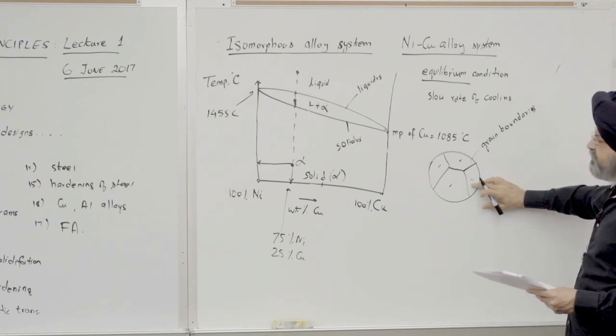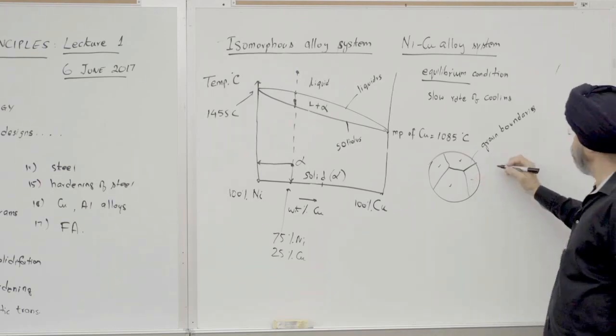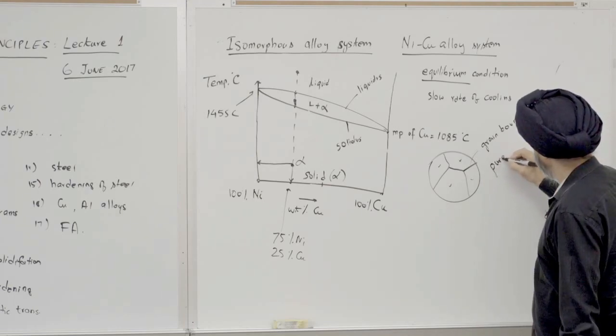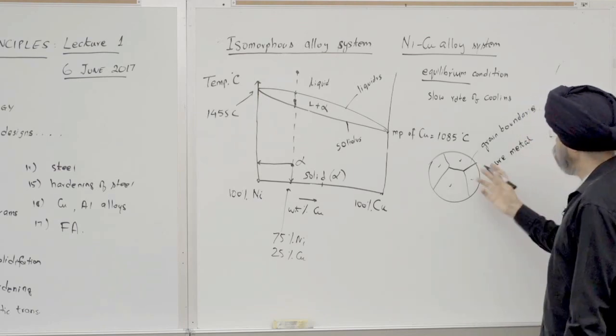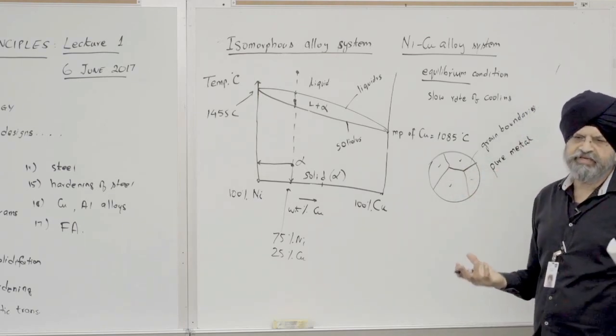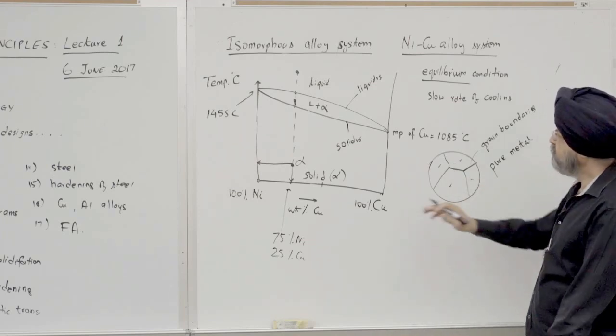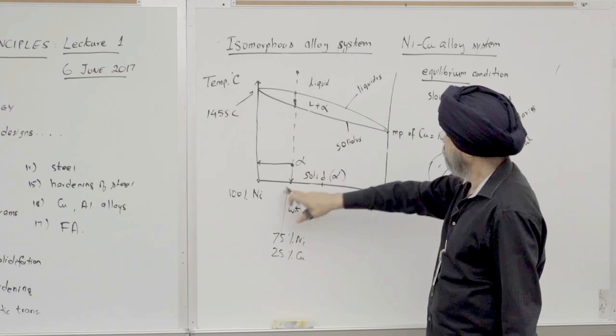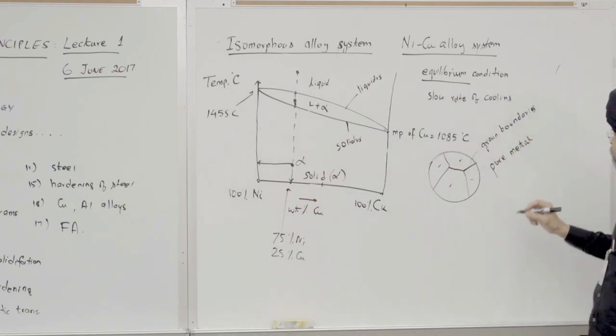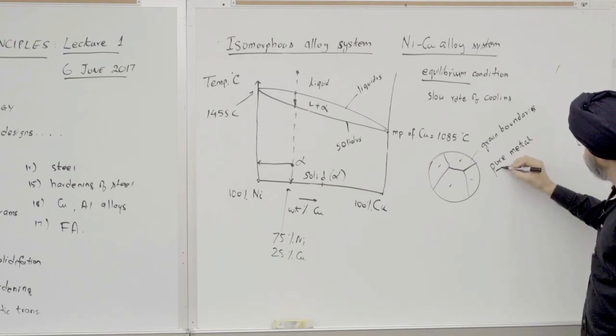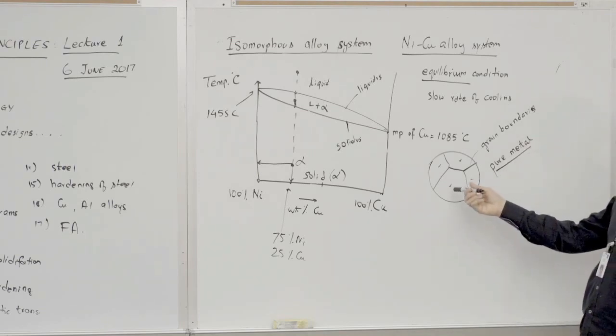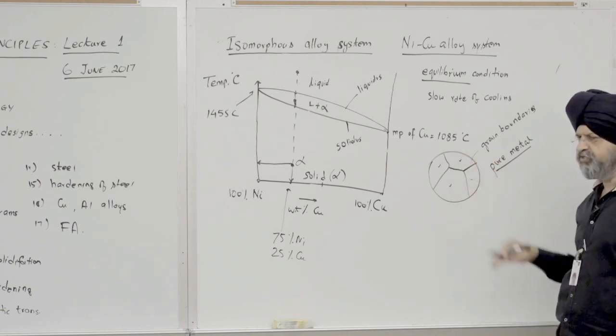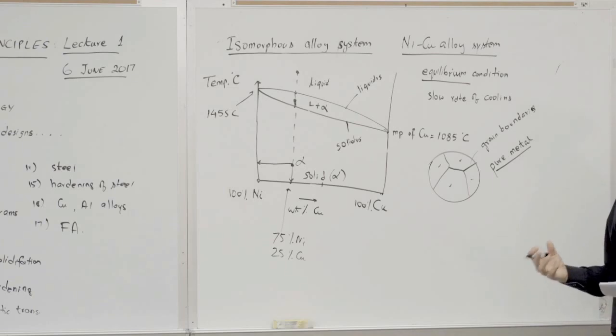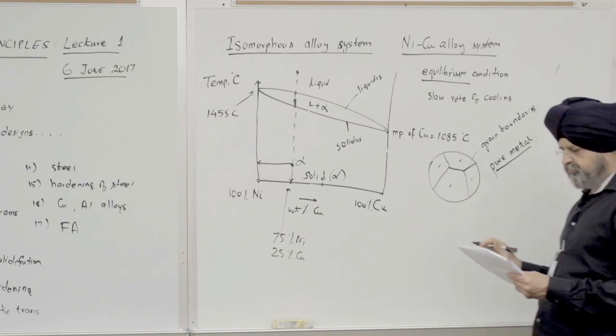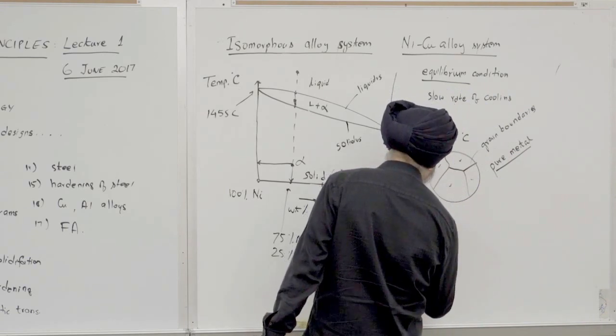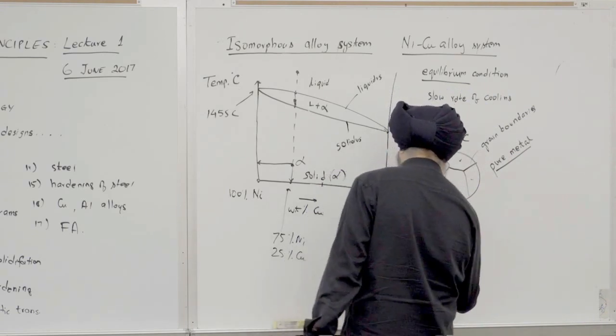So looking at this microstructure, you would think that this is a pure metal because all these grains look the same. The thing is featureless except it has grain boundaries. So for this isomorphous alloy system, this binary system, the microstructure looks like pure metal. You can't tell where the nickel is and the copper is. They're all mixed up. It's a solution, like adding sugar to water. But this binary alloy will be stronger than its parents, nickel and copper.